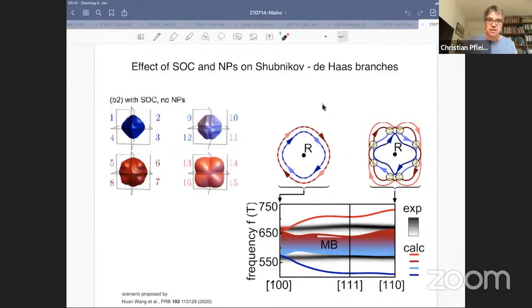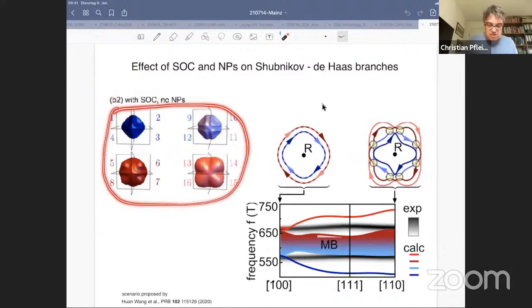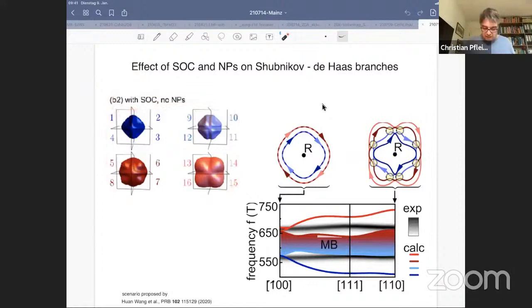Let's do the conventional thing. When we switch spin-orbit coupling on, we get 4 Fermi surface sheets around the R point, right? And as we're aligning the field along the 100 direction, these are nicely separated, so we expect 2 frequencies, right? But they're close by, and so we expect some breakdown, right? So we expect additional frequencies because there is some possibility, some kind of probability for the electrons to tunnel from one orbit to the other, right? This is shown here in the center, right? There's a certain weight, right? But you expect a lot of intensity, basically somewhat distributed between the two.